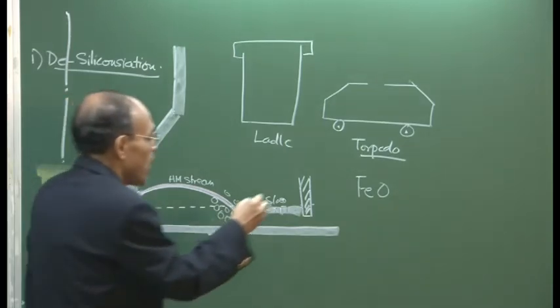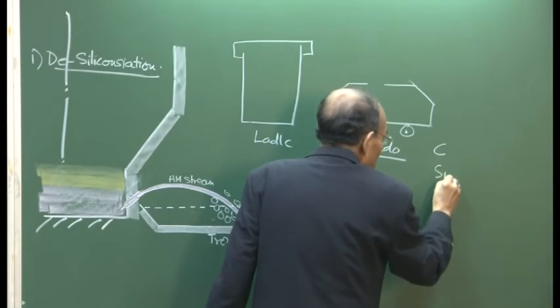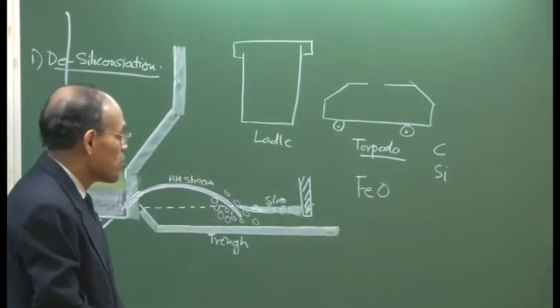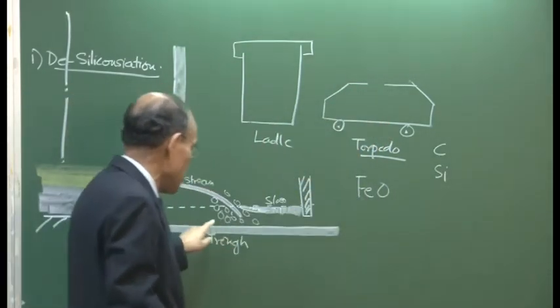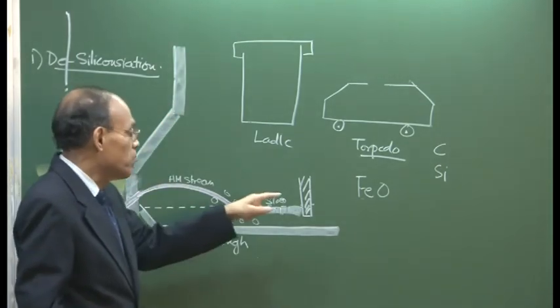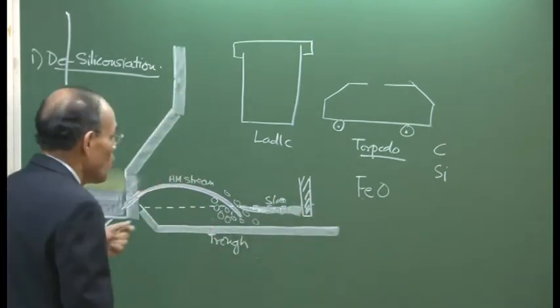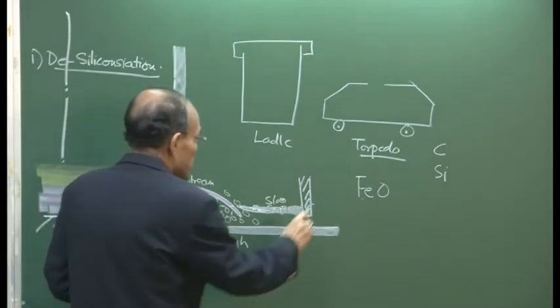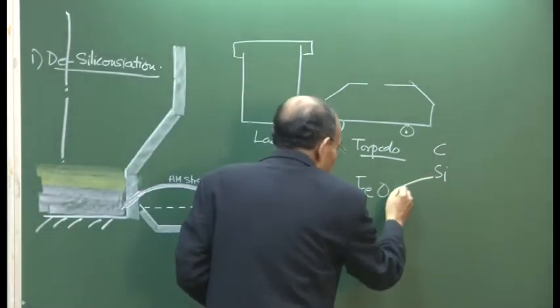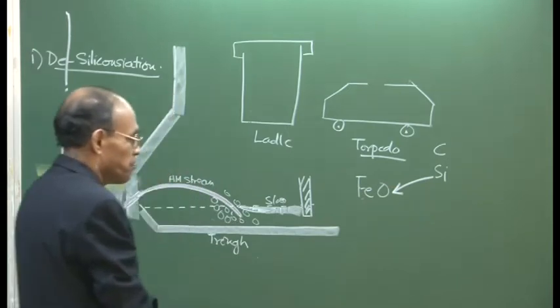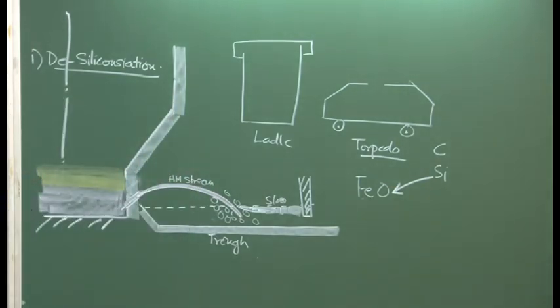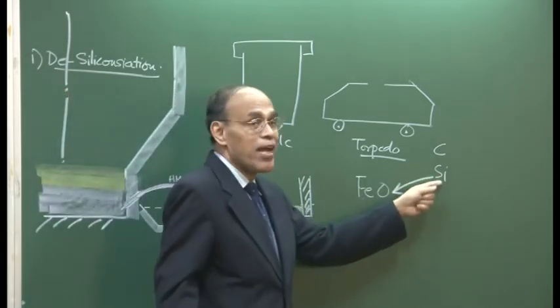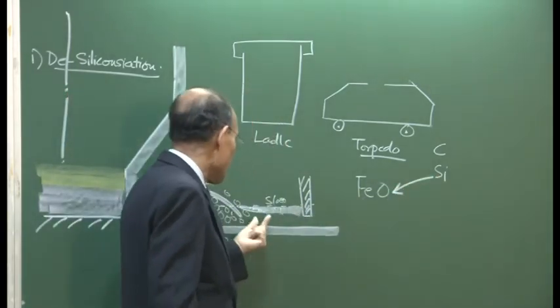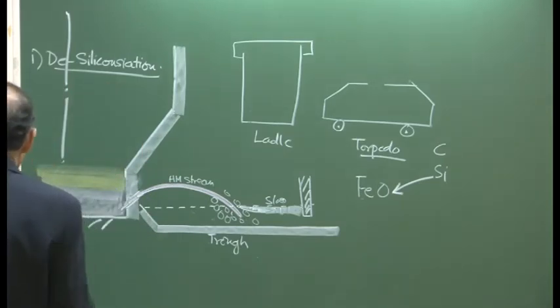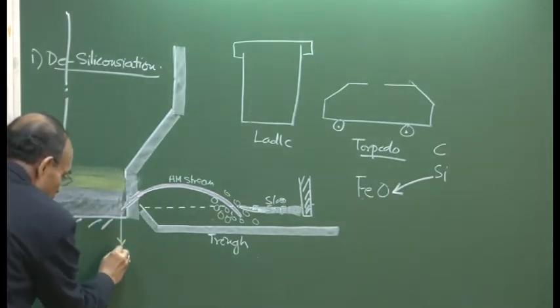Now, you have carbon and you have silicon dissolved, but silicon has much higher affinity towards oxygen. So, the moment FeO is there, and FeO is a low melting point constituent that we all know, this silicon will predominantly react with the oxygen, and it will try to snatch the oxygen, because if you look at the Ellingham diagram, at about 1350 degree centigrade, that is the hot metal temperature in India,